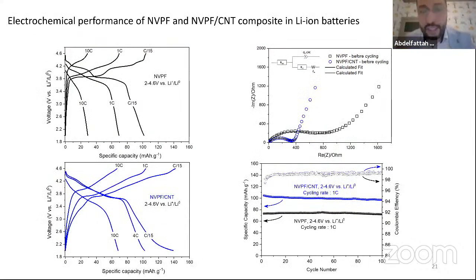In order to explain the source of this increase, we can see that the charge and discharge voltage profiles are different. Here we can see that we have 3 plateaus for the one with carbon nanotubes. And when we make impedance measurements, we can see that the one with carbon nanotubes shows lower resistance, which means higher electronic conductivity. We also make the cycling at 1C, which is a very fast regime. It means we are charging and discharging the material in 1 hour.